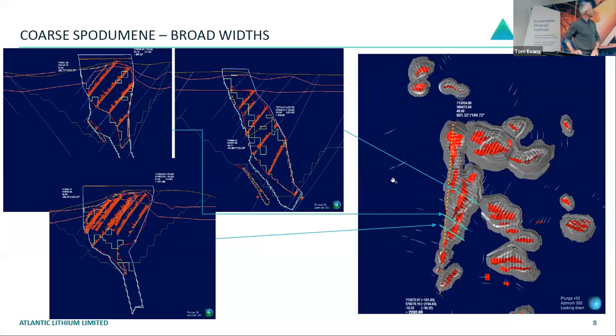So here are some cross sections of the pegmatite. On the right here in red, you can see the 0.4 mineralization shells. So these are the pegmatites at greater than 0.4% lithium oxide. And in gray are the pit shells that have been designed around that. And then some cross sections through there. So this is what we call our main Ewoyaa trend, that north-south trend.